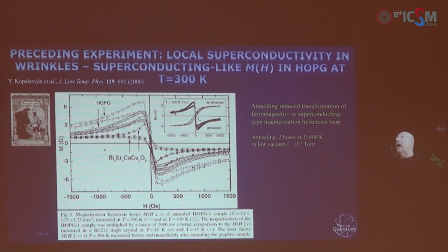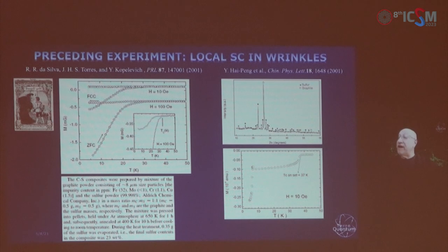And these measurements are beautifully compared with the measurements obtained on a usual piece of superconductor, which also has a layered structure, and the very remarkable effect which immediately indicates that the superconductive activity is of a local nature: the graphite signal must be multiplied by a factor of 2,000 so that the data become compelling.